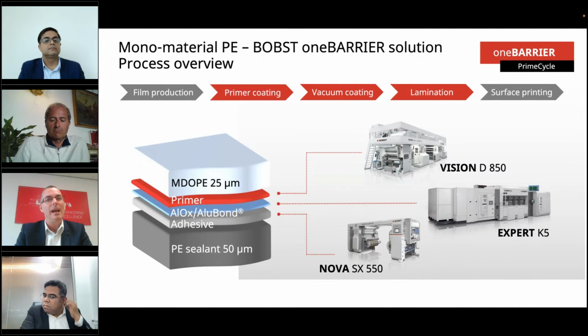So with these market trends and the performance requirements in terms of barrier, this was really the foundation for developing our one barrier PE solution. The image on the left illustrates the structure of the one barrier prime cycle solution, along with the machines that have been used to optimize the associated production steps. We start with wet coating that we apply onto the MDO-PE, and this was applied on our Vision D850 platform. From that, we then moved to vacuum technology, where we applied the vacuum coating layers on the Expert K5 metallizer. And finally, we conducted lamination on the Nova SX550 laminator, where solventless lamination was selected to reduce any additional thermal impact on the polyethylene-based structure.